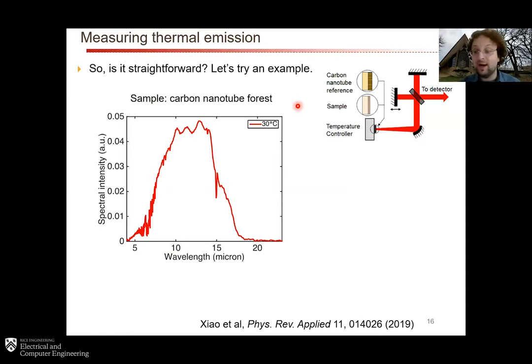It has very, very high emissivity, almost 1, across a very broad range of wavelengths. It's very black in the visible, it's very black in the infrared, and so forth. So this is, for all intents and purposes, a black body. So we put this black body right here, we send it into our FTIR spectrometer, measure what the detector sees, and then we Fourier transform that to obtain this spectral intensity versus wavelength.